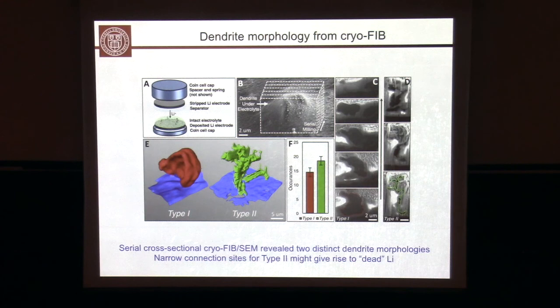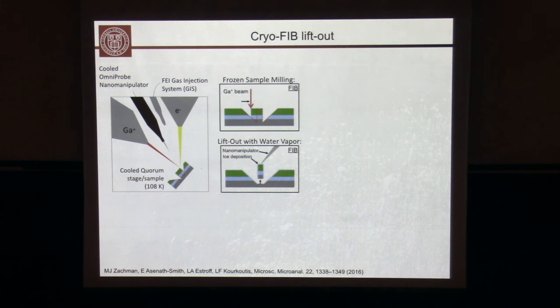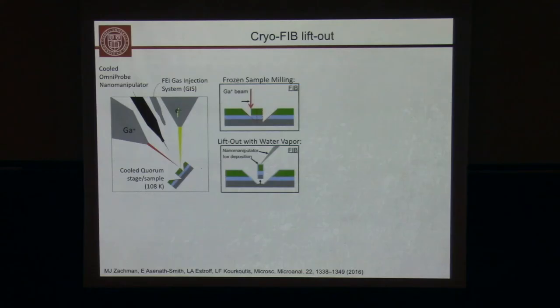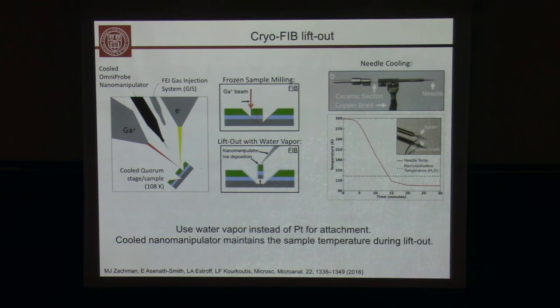Now, these are very different in structure. What is different in their chemistry? And in order to do that, we actually need to get higher resolution information in chemistry that we can get from EELS. So as we talked about, thickness of a sample is a huge concern. We need to get very thin lamellas. And the way we do that, this is our focused ion beam. This is the beam of gallium ions. We have an electron beam that images the material at the same time. But what's new here is that the needle that allows you to extract a small lamella is now cooled to liquid nitrogen temperature. And that means in this process, you remove material from the left and the right, create a lamella of our liquid-solid interface, you attach the cold needle with water vapor, and you can extract it while maintaining it at liquid nitrogen temperature or at least below the vitrification point.